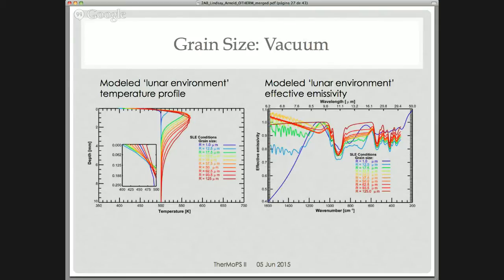modeled for the vacuum environment. Here we seem to have a less clean story. The neat thing is that we see the effects of the lunar environment. So we see the Reststrahlen bands getting deeper, especially for the smaller grain sizes. So that's blue here and blue here. That's neat. But we have some odd, unexplained things, like the behavior of the Christiansen feature is a little odd.